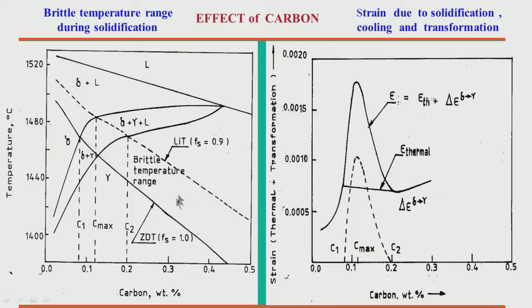Again I am mentioning this temperature region between solid fraction of 0.9 and 1, the temperature between liquid impenetrable temperature LIT and ZDT, zero ductility temperature, which is corresponding to the completion of solidification temperature. This is the actual solidus temperature. So, this is the brittle temperature region.